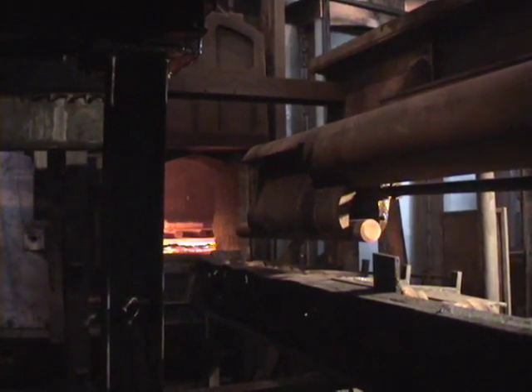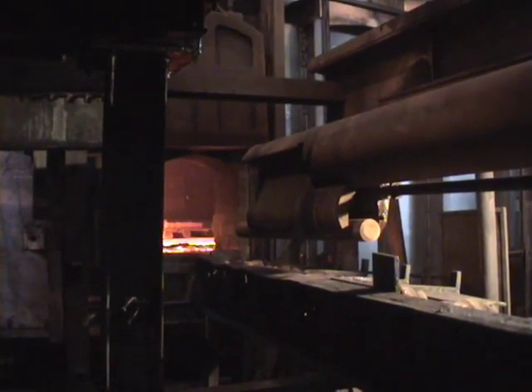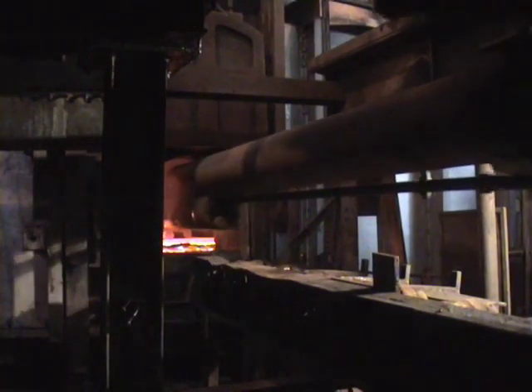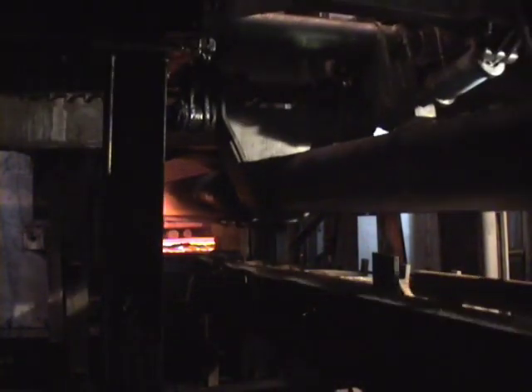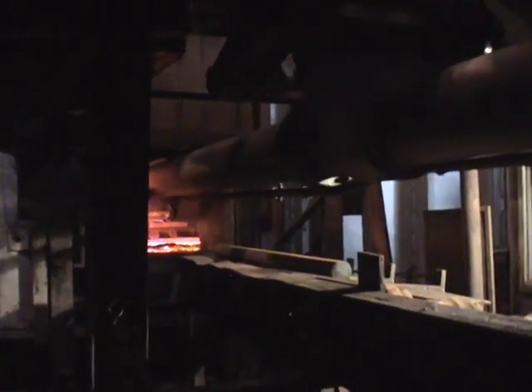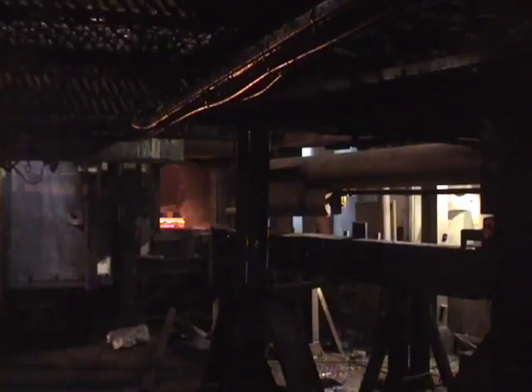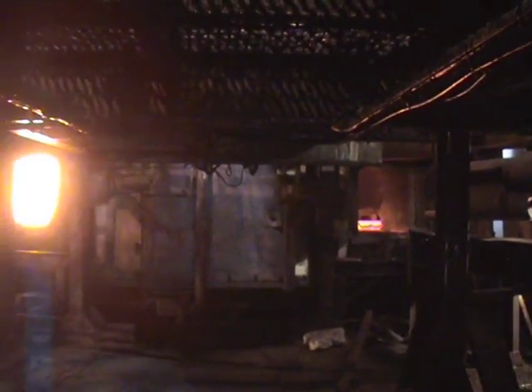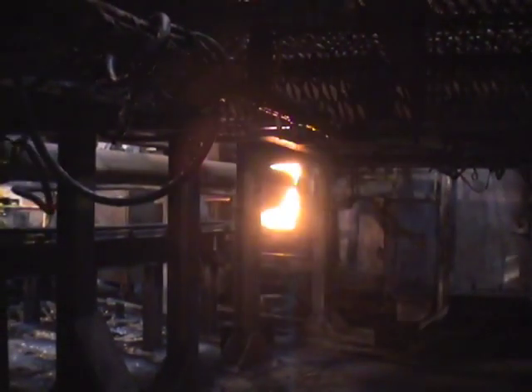Timed gaps are left between each billet, allowing up to 160 to be heated in the furnace at any one time. The furnace is heated by a combination of natural gas and preheated air. A heat exchanger under the floor uses the hot waste gas to bring the temperature of ingoing air up to around 450 degrees Celsius. The furnace is divided into 4 zones with individual temperature settings. These are computer controlled to bring the billets up to rolling temperature, which is usually 1130 or 1250 degrees Celsius.